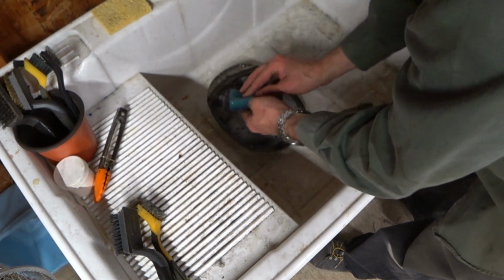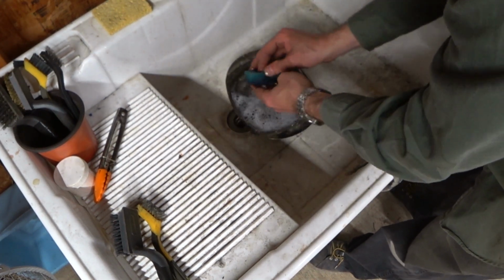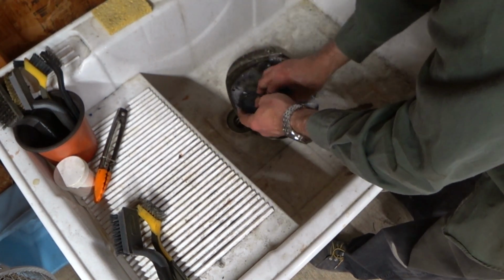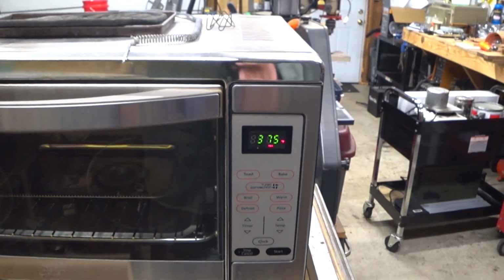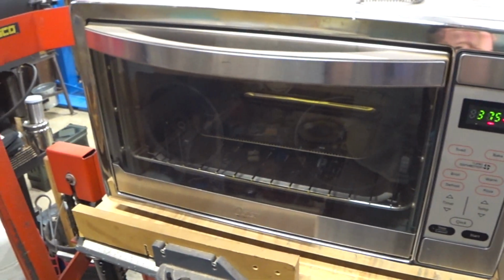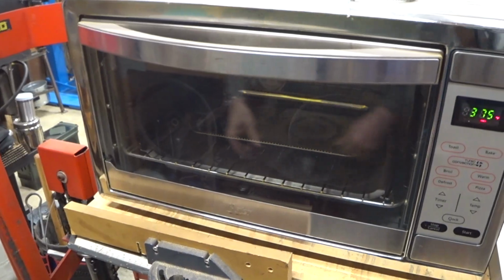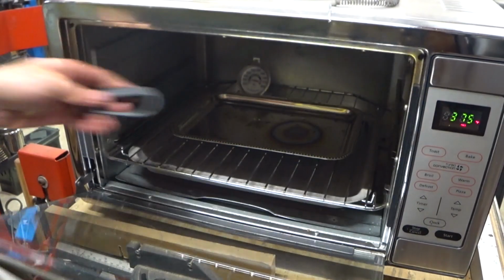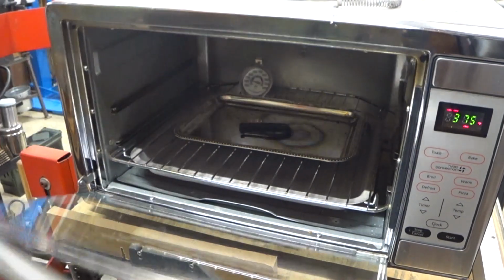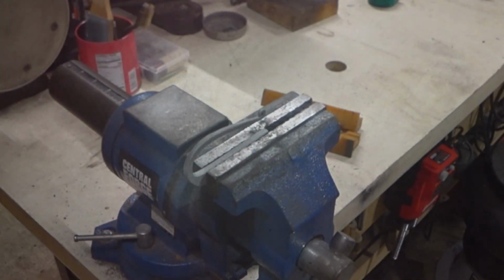So it goes into a little soap and water with a scrub in order to get any oil residue off before the temper. It's debatable whether or not a temper is needed for a Flint striker. I think temper, at least a light temper, is a good idea to make a tool that's not too brittle. This is totally unnecessary, but I usually go to the sandblaster next to get a nice uniform finish.